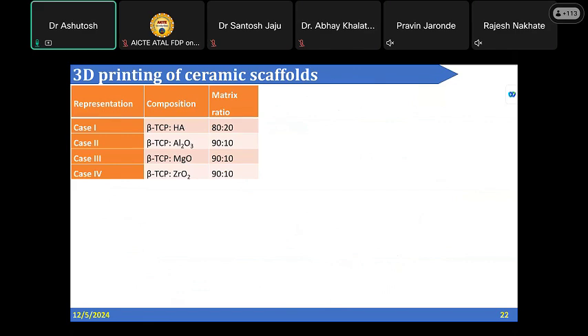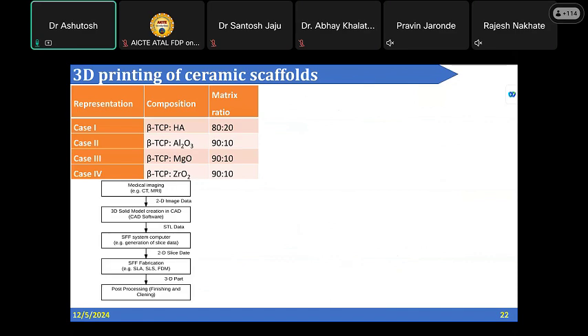Now, for 3D printing of ceramic, the data which I am showing you is my PhD data. I used four different cases: beta TCP, that is the beta form of tricalcium phosphate, and hydroxyapatite, HA, in a ratio of 80-20. Then I used beta TCP and aluminum oxide in 90-10, beta TCP and magnesium oxide in 90-10, and beta TCP and zirconia in 90-10 ratios. This diagram I already shared in the first slide, where we use the CT scan, convert it into a CAD model, then do the STL formation, then slice it, then give it to the 3D printing process, followed by post processing.